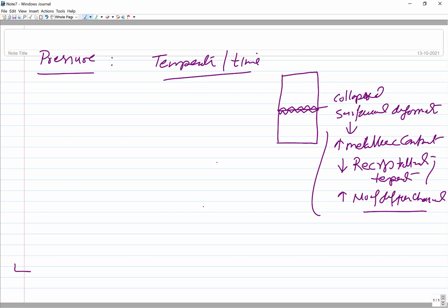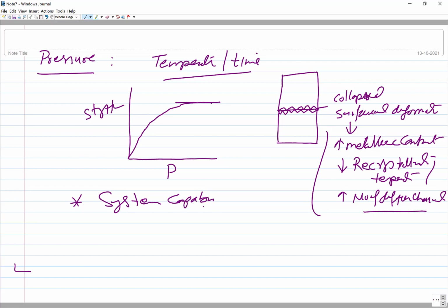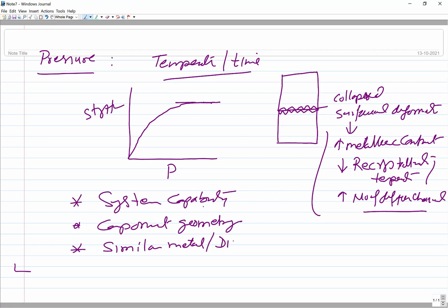These are the three things being affected by the pressure. So increasing pressure in any case helps in improving the diffusion bond formation. In general, increasing pressure increases the joint strength up to a limit, and thereafter it stabilizes. However, the maximum magnitude of pressure that can be applied depends on the system capability. The second is the component geometry itself, because the component may not be able to sustain high pressures. And the third is the kind of joint being made, whether it is a similar metal joint or a dissimilar metal joint.